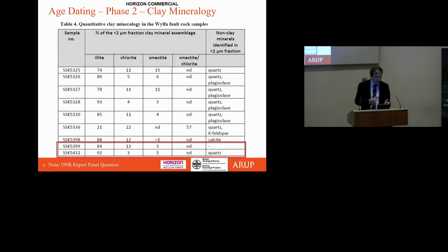So the next stage was that we needed to take some of the samples and take them away to do some age dating. So we're going to have absolute age dating. And so we had to do some mineralogy, looking at what the clay minerals actually are in the gouge. And what we found was that the majority of the samples, at this very small micron level, only 2 micron size and less of clay, was dominated by illite clay. And it's in the order of 75 to 90% of the clay in the clay gouge was illite. That was ideal, actually, because illite has a lot of potassium in it, and you can use the method potassium-argon dating, which is quality assured. Laboratories around the world use it, lots of experience, and ideal for the project.